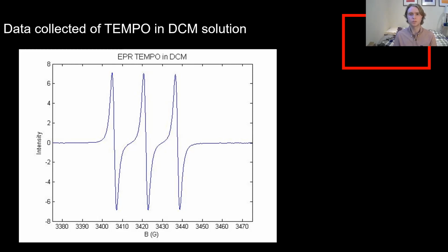Normally, as much as the peaks broaden, they also get shorter, and that's actually proportional. So the integration should be about the same, and the integration is what's really important for the quantitative data collection. Another thing that is important, though, is if the line broadening gets too big, the peaks might start to overlap. And if the peaks start to overlap, that would begin to cause a problem for quantitative data collection.